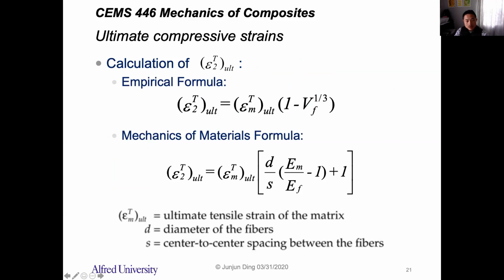And to find out the ultimate strain in the two direction, people commonly use the empirical formula, which is the function of the ultimate strain of the matrix times 1 minus volume fraction of the fiber to 1/3. Right? So this is the empirical formula based on experience and experimental data. Okay?